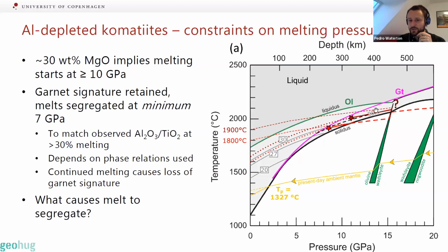If we have temperatures much higher than this, it actually gets a little confusing because projecting back from where the melt would have segregated, you know, 30% melting before the garnet out curve, you actually hit this olivine-wadsleyite transition before you hit the solidus. And so it's really not sure what would happen here, whether there are melts in the transition zone, whether melts would actually be freezing in the transition zone or continued melting. But either way, probably somewhere in this ballpark of potential temperatures, you can actually hit all of these constraints.